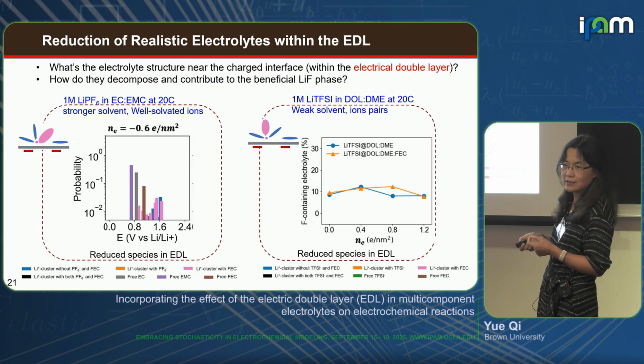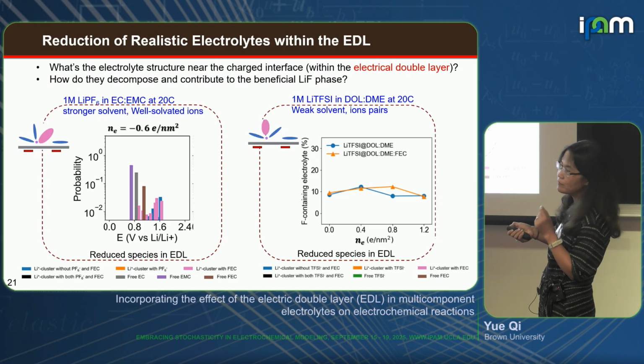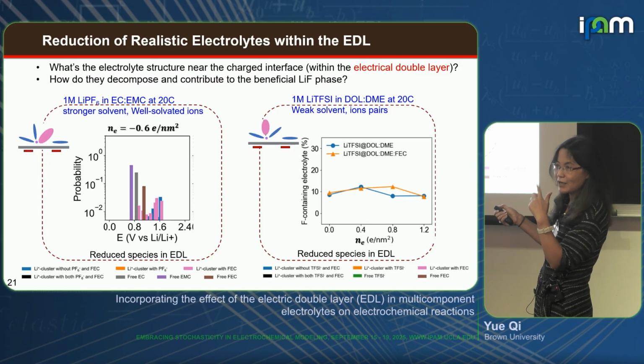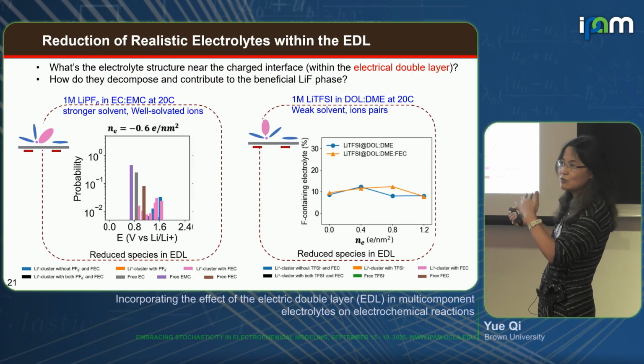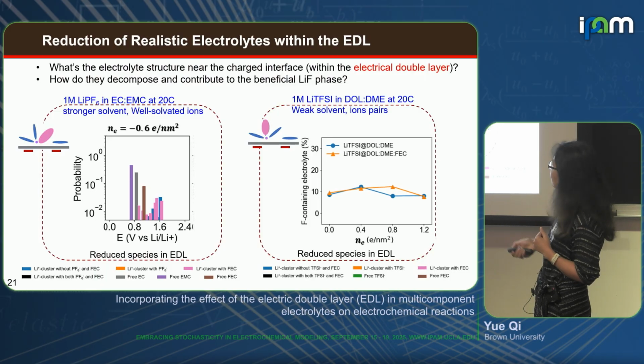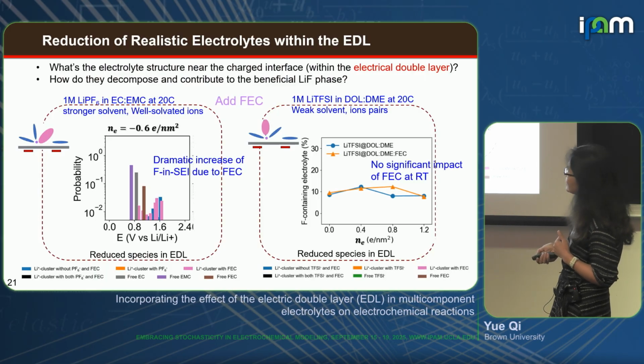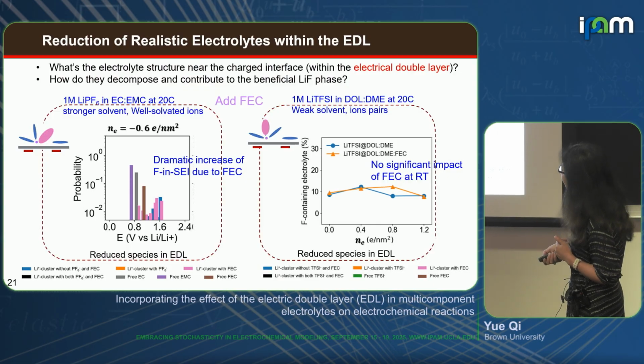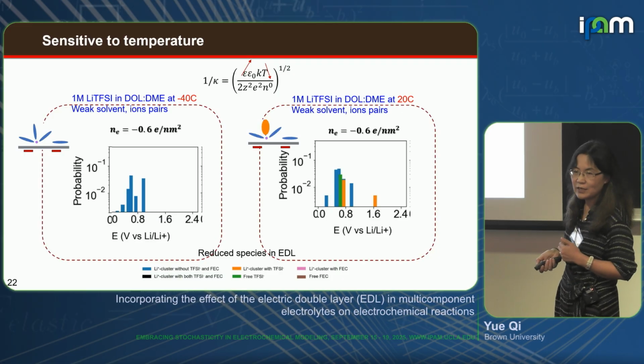So now I want to add this additive. All right, I wanted to add this FEC because FEC has very strong binding with lithium, and so they just show up in the double layer region and get reduced. And this one's interesting because FEC also comes to the double layer in the weak solvent, but they kicked out the ion. So if we look at the fluorine species, we didn't see much change, right? The composition has changed, but the contribution to the fluorine species has changed from ion contributed F to FEC contributed F, right?